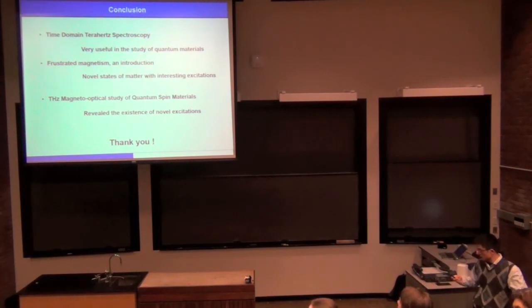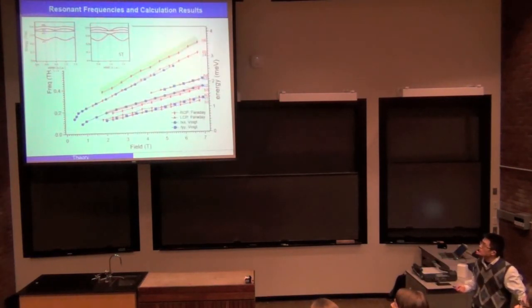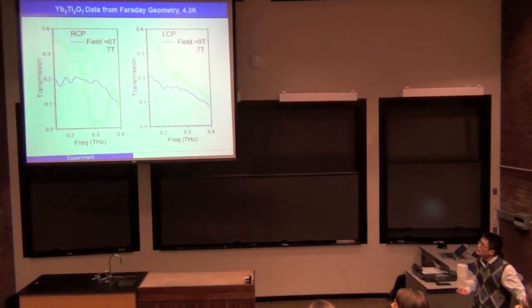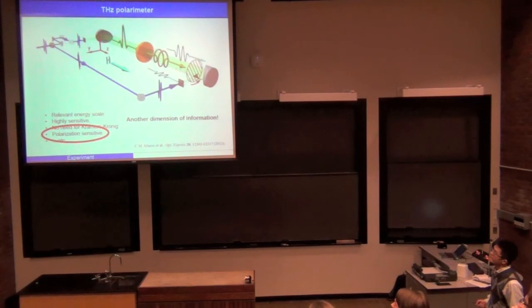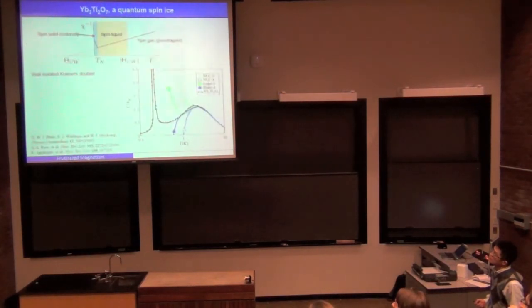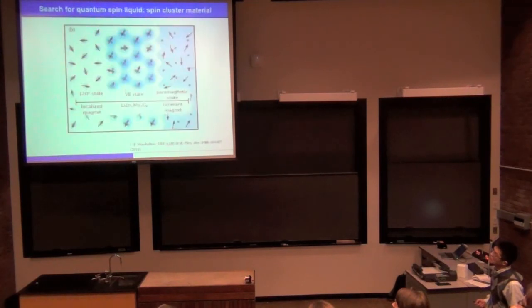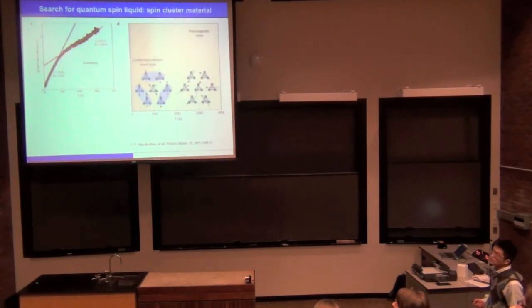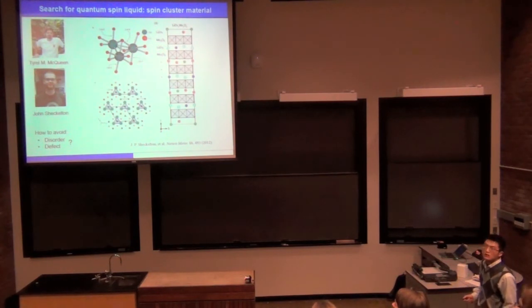Could you go back to the molybdenum clusters that you had earlier on? So they were triangular in shape, right? And you had an odd number of electrons to give you the spin 1/2 on a cluster. Is that right? That's right. So in addition to the spin degeneracy, wouldn't you have an orbital degeneracy because of an odd number of electrons in a triangular structure? The triangle C3v supports twofold degeneracies. Well, I should say this spin is not localized on a particular ion. Instead, it's shared by the cluster. I understand, it's a cluster.